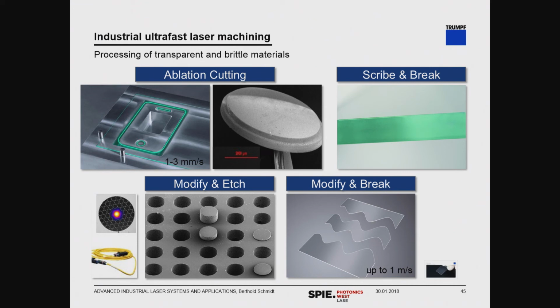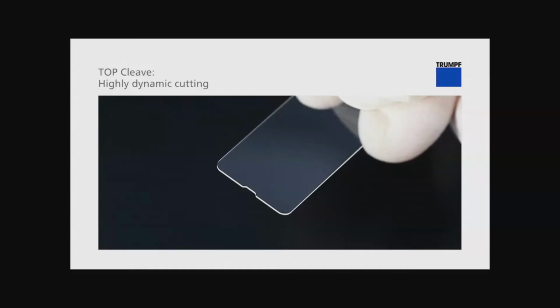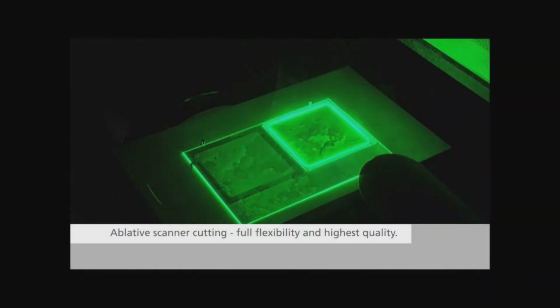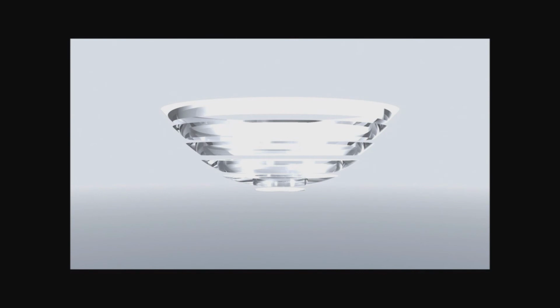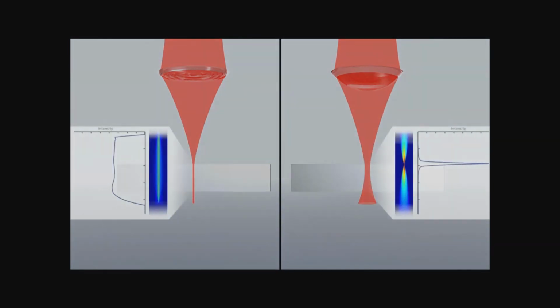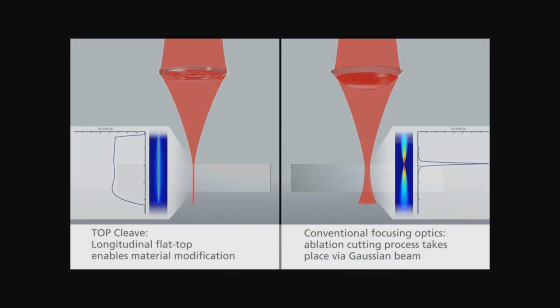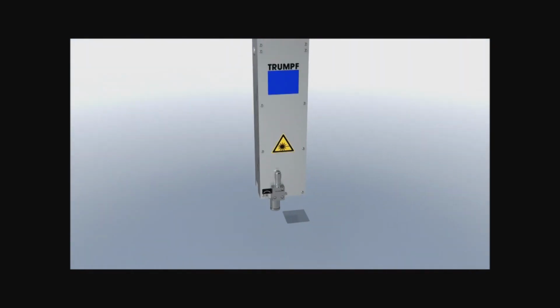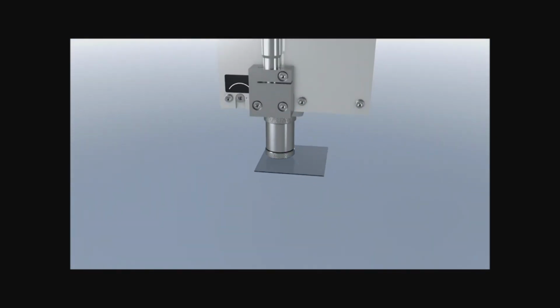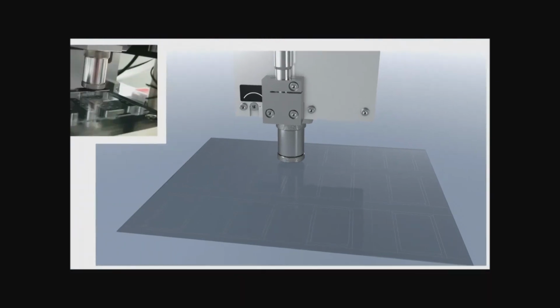Okay, so the TopCleave optics is in general a technology where we use a diffractive optical element to create a Bessel beam, and this Bessel beam then is able, here we go, to, this is still using an ablative scanner cutting with a standard Gaussian beam. Now you see here the DOE, how it is formed, and this DOE with a focusing optics creates a fine Bessel beam that creates more or less a distortion in the material when you move it with a picosecond laser through the material, and this material modification then is creating more or less an additional strain in the Gorilla Glass, for instance. And now you see it in real time here.